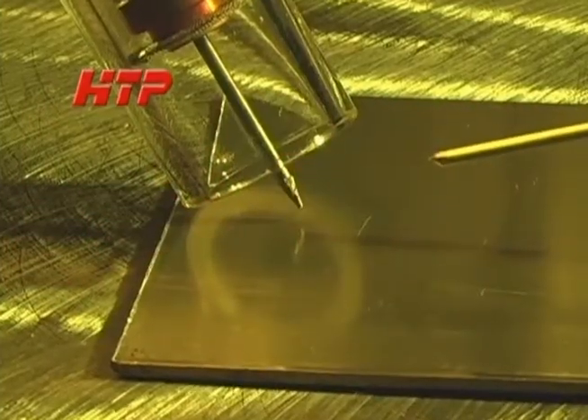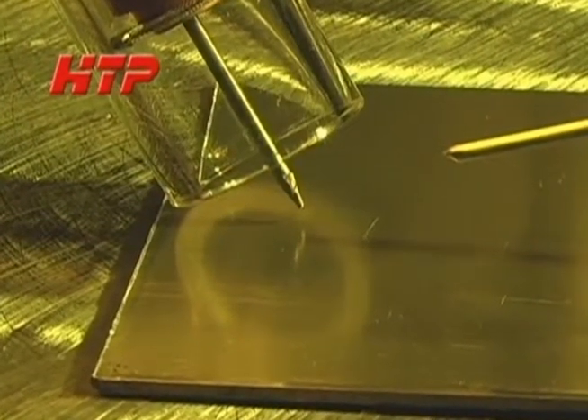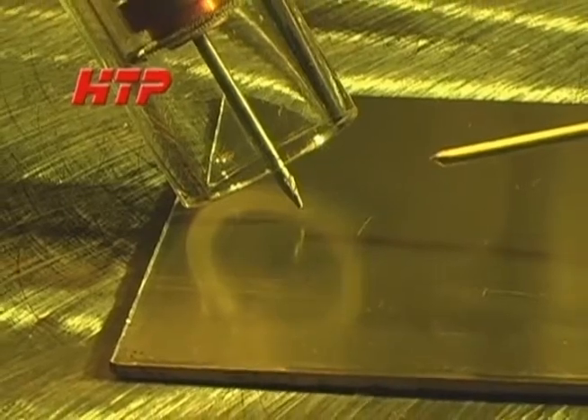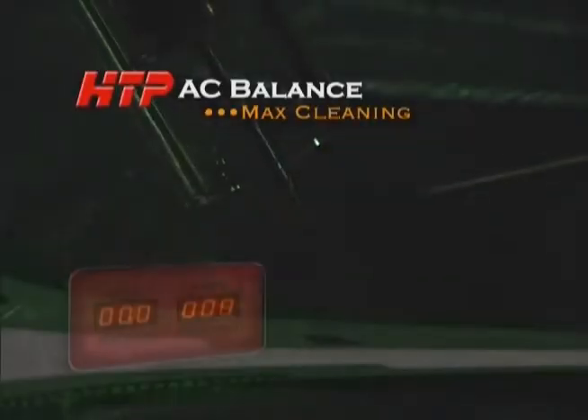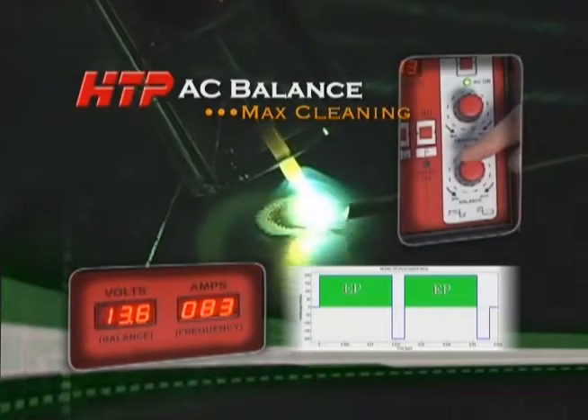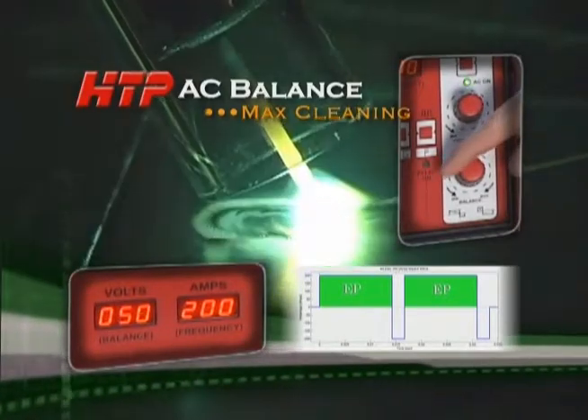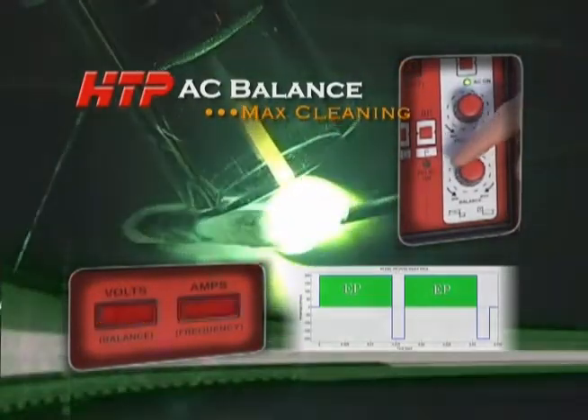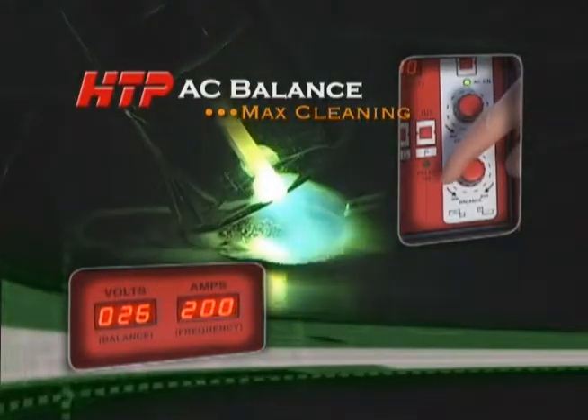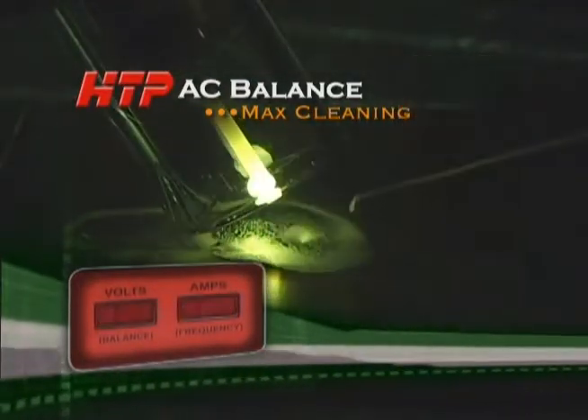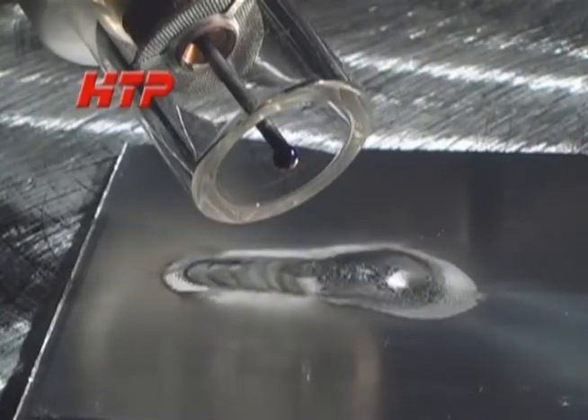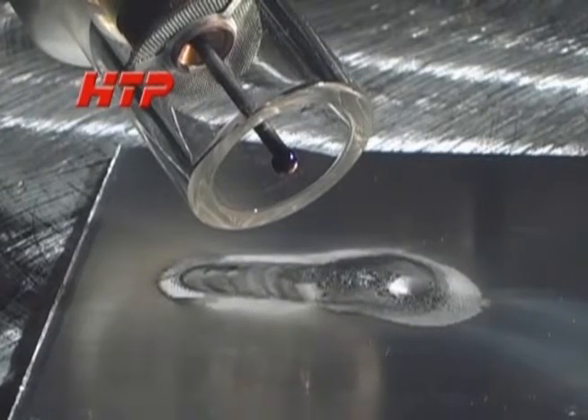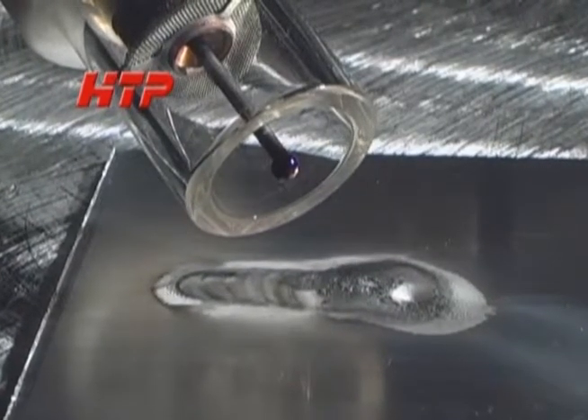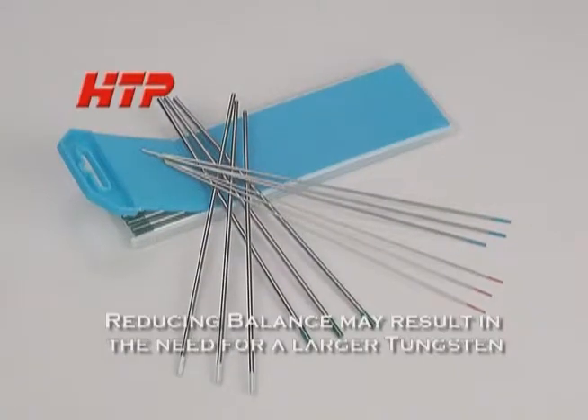We start welding at 60 amps with the balance set to 65%. A 1/16 inch tungsten works just fine. As we decrease the balance, you can see the tungsten starts to overheat and melt at about 40%, and by the time we get to 25%, it is fully molten. You can see how the melting tungsten has contaminated the last portion of the bead. If you reduce the balance, you may have to go to a larger diameter tungsten.